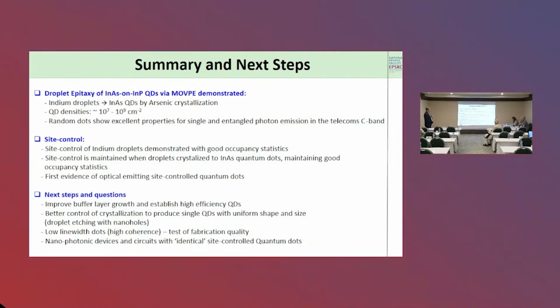control. So site control of indium droplets has been demonstrated with good occupancy statistics. Site control is maintained when the droplets are crystallized into indium arsenide quantum dots, maintaining the good occupancy statistics. And we have the first evidence of optical emission of site control by this method.